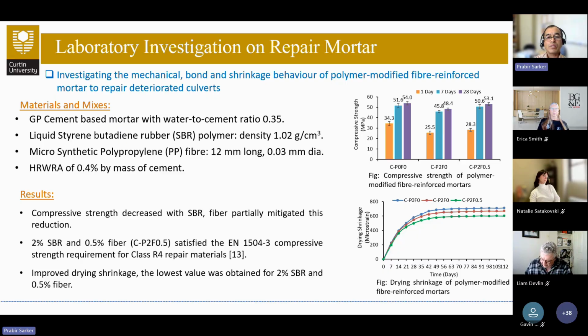The first set of results are for the control mortar, and the third set of results are for 2% SBR and 0.5% fibers. We could see that it reached 50.8 MPa at 28 days and 28 MPa at 1 day strength, which satisfies the requirement for a structural repair mortar.